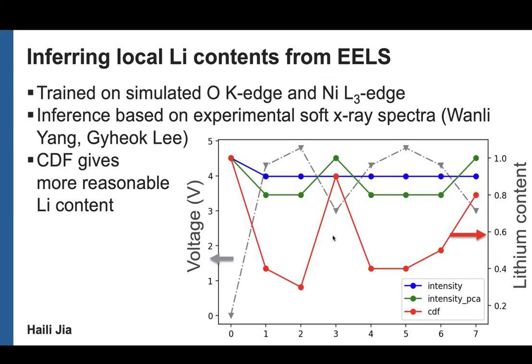And this is going to be a problem for many different characterization techniques, spectroscopic characterization, or even scattering, because sometimes there's a slight difference in lattice parameters, so your XRD peaks will be off. Sometimes there might be temperature effects, so your Raman peaks will be slightly off, and so on. So, thinking deeply about how you featurize your data and testing for realistic noise and errors is important.